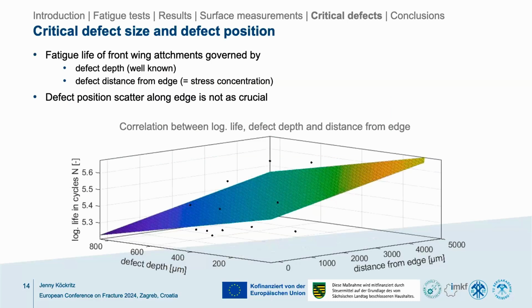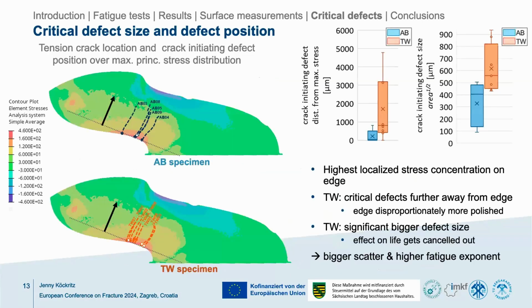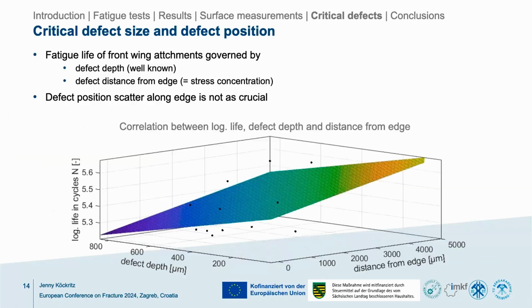We can kind of correlate for this specific use case that the fatigue life of the individual specimen is mostly dependent on the defect depth, which is not very surprising, and the defect location in terms of distance from the edge. The scatter along the edge, which you can also see here, didn't play such a big role for this use case. However, the correlation is not very good. I know that, but still, this is the one that shows the best correlation here.